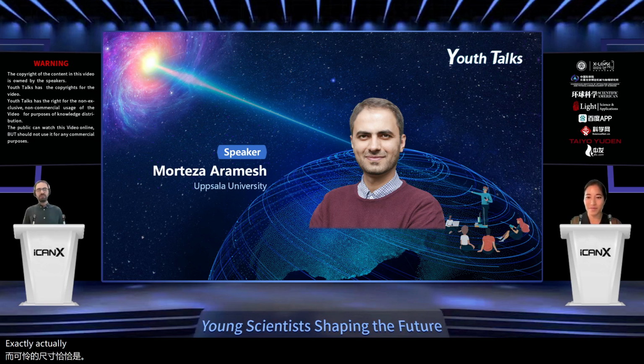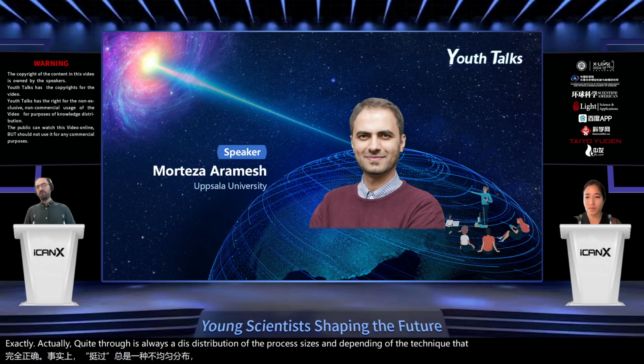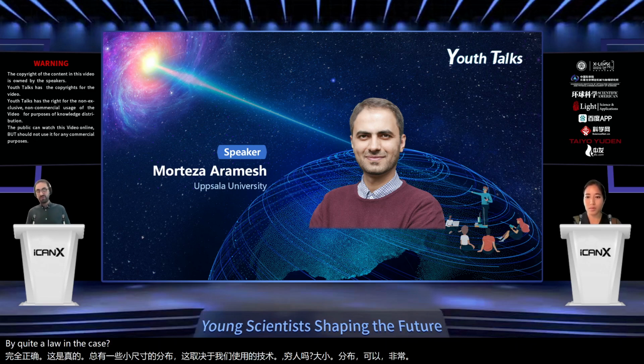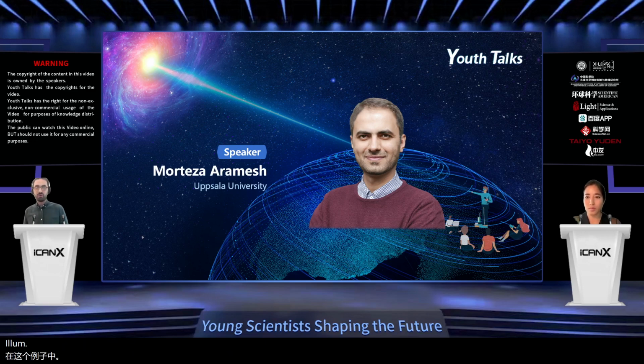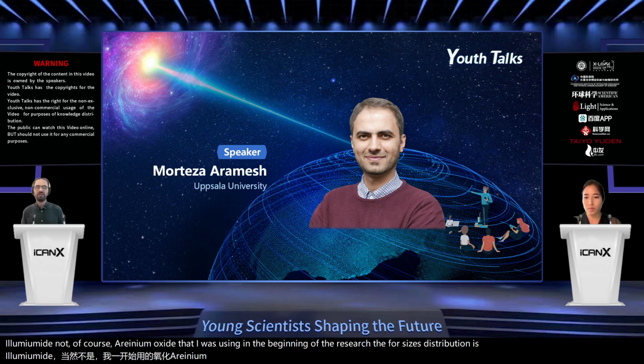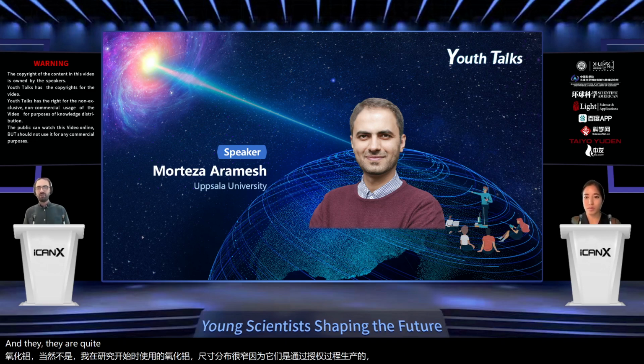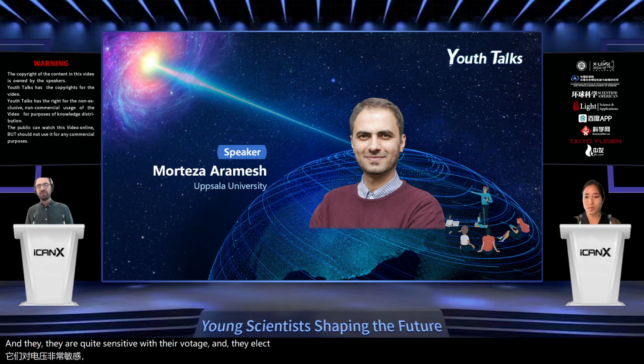Exactly. That's actually quite true. There's always a distribution of the pore sizes, and depending on the technique that one uses, the pore size distribution can vary by quite a lot. In the case of the nanoporous aluminum oxide that I was using in the beginning of the research, the pore size distribution is quite narrow. They are produced by the anodization process, and they are quite sensitive to the voltage and the electrolyte that are being used in the anodization process. It's an electrochemistry process, so it is actually quite accurate to make pores of the same size.